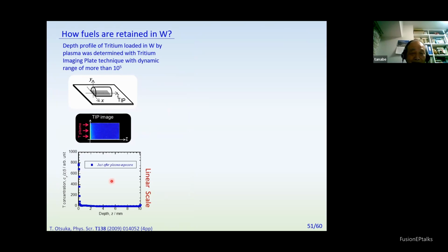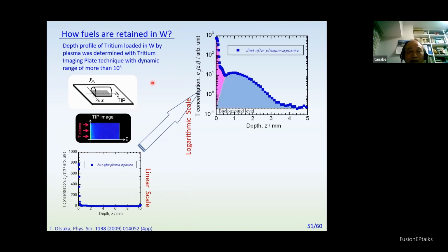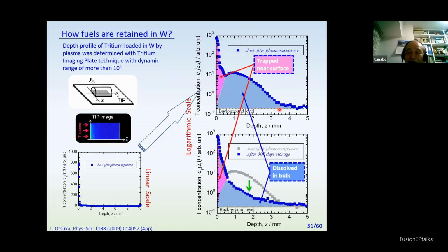This is a linear scale, but if you go to logarithm scale, because tritium can be made with a very wide dynamic range, the profile looks like this. This is surface trapping, near surface trapping, and this is just the solution. This clearly appears after 30 days, where only this part, the dissolved hydrogen, is released, while trapped hydrogen near surface remains. This clearly shows that most of the deuterium remaining in tungsten is trapped.